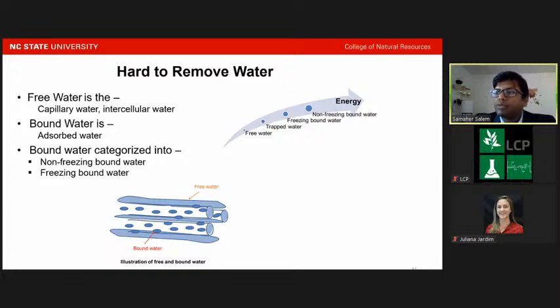The cellulose-water hydrogen bond has higher energy than the water-water hydrogen bond in the fiber, which increases the local minima corresponding to the bound water, which is lower than the free water. That is, the potential energy of the bound water is much, much lower than the free water, and that's why it takes higher energy to remove the bound water compared to the free water. So, does it increase the average lifetime of the cellulose bound water?